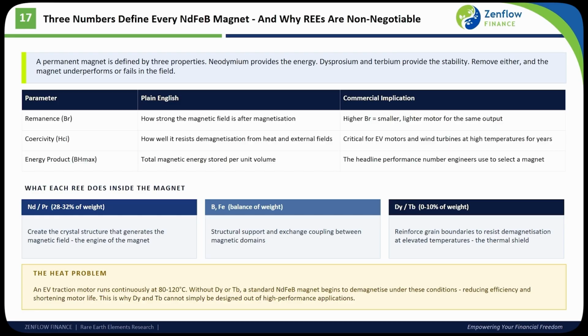They are the thermal shield. Here is a critical point highlighted in the heat box problem. An EV traction motor runs continuously at 80 to 120 degrees Celsius. Without dysprosium or terbium, standard NdFeB magnet begins to demagnetize under these conditions, reducing efficiency, generating heat, and shortening the motor's operational life. This is precisely why dysprosium and terbium cannot simply be designed out of high-performance motor applications. The heat problem is not an engineering footnote, it is a fundamental material science constraint.